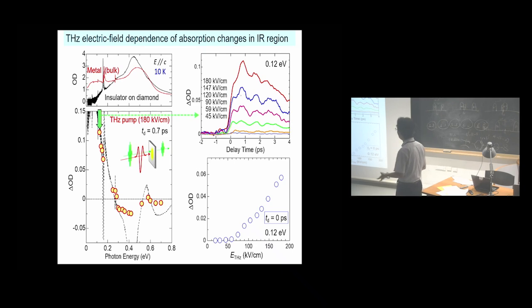After the photoinduced insulator metal transition, the metallic state is further stabilized by the molecular displacement. But the time scale of the molecular displacement is about, the period is about 1 picosecond or something like that. So the insulator metal transition occurs in the faster time scale. Okay. Let me discuss just after this slide.